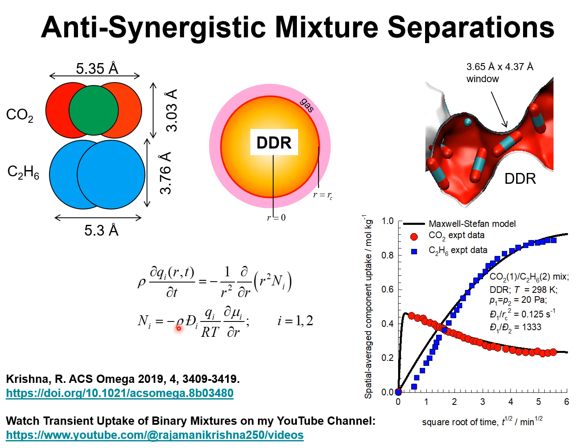framework density of DDR. The experimental data can be matched taking the ratio D1 divided by D2, the ratio of the Maxwell-Stefan diffusivity of CO2 to the C2H6, to be 1333.